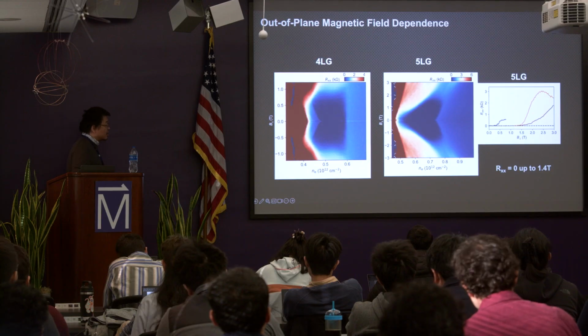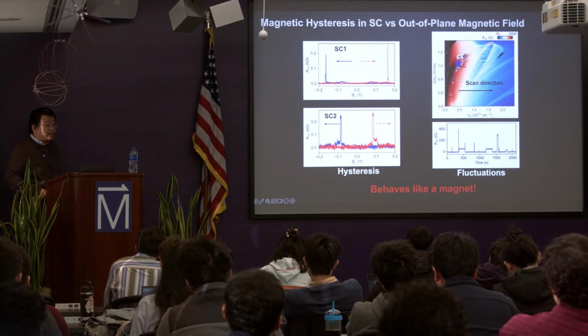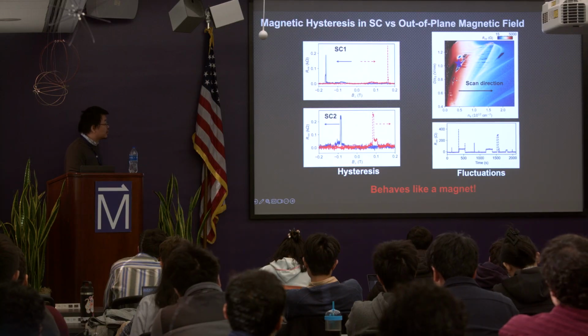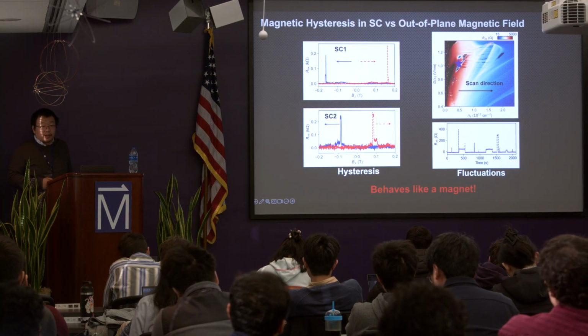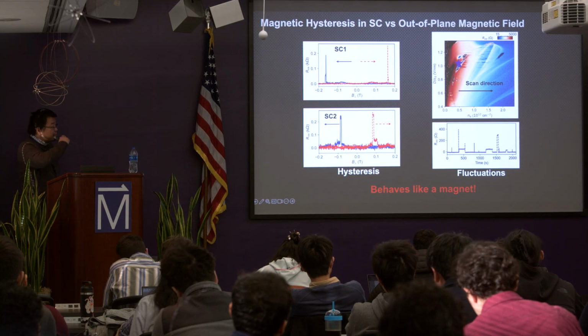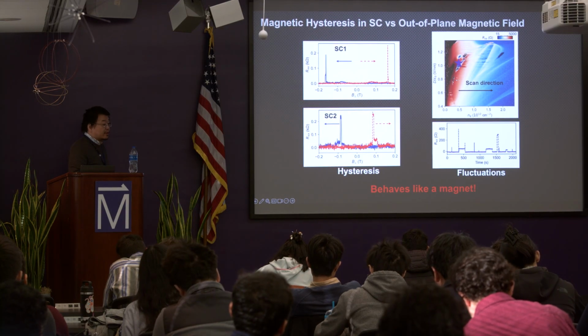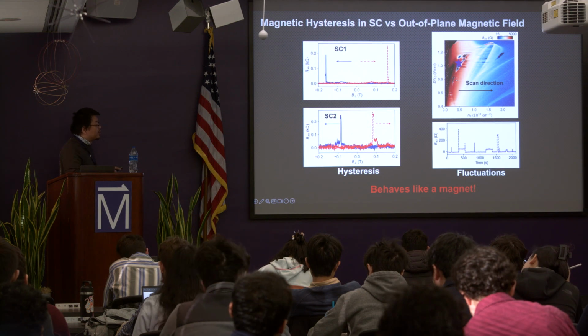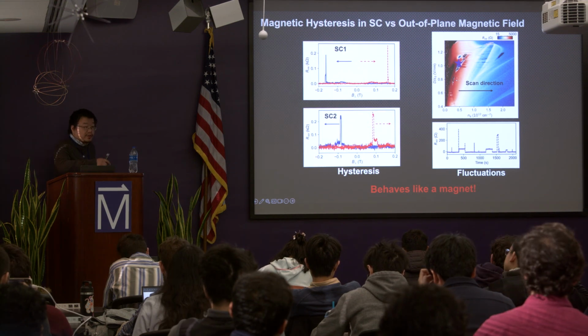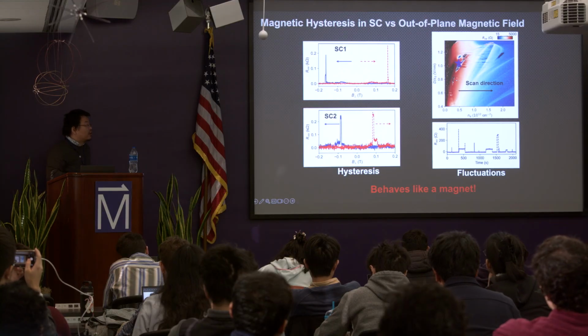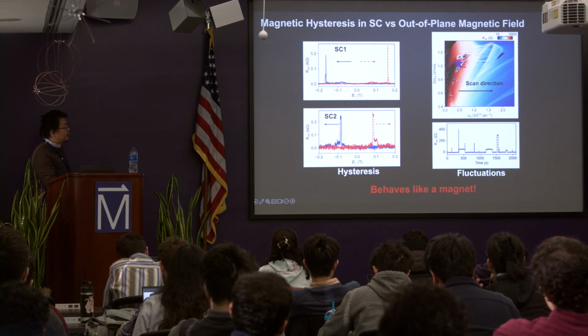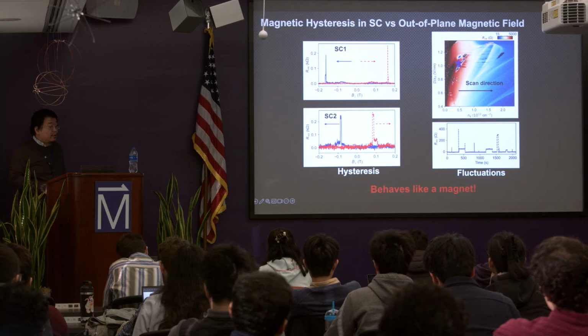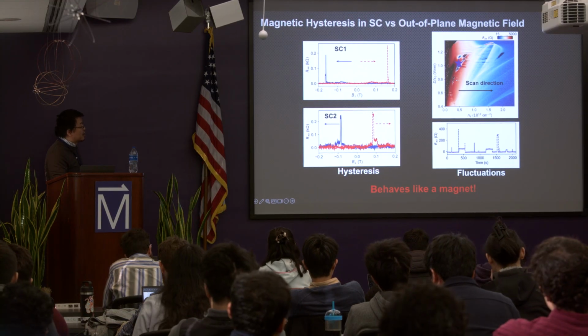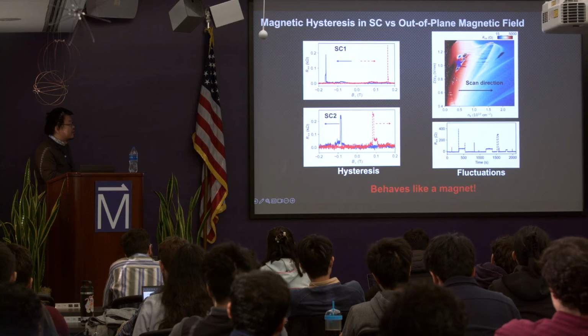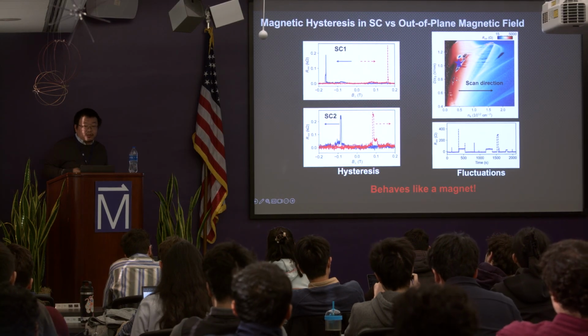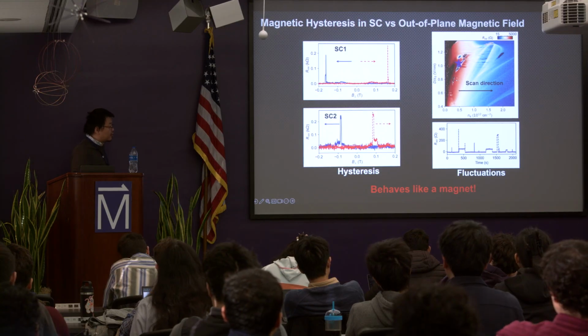And even more striking, other than surviving up to a very high out-of-plane magnetic field, it shows hysteresis behavior in the superconductivity domain. So what do I mean by hysteresis in a zero resistance state? Basically you start with zero resistance, and then you start sweeping the magnetic field. At some point, it has a very sharp jump to finite resistance, and then jumps back to zero. Then you sweep it back, so it starts at zero, jumps to some certain value, and then jumps back to zero. So this really looks like a magnet, right? It's a superconductor, and at the same time it also looks like a magnet.